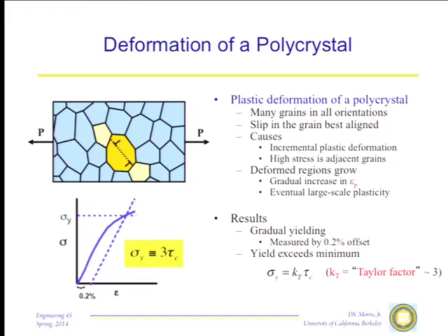In fact, some of those internal stresses will be very, very close to the yield strength, because you have to have a stress above the yield strength to get the grain to deform so that it relaxes itself. So if you just take a piece of material that you whack with a hammer, for example, and deform, and you look at that, then you have grains within that material which are right now under loads that are right at the yield strength, just not above it.